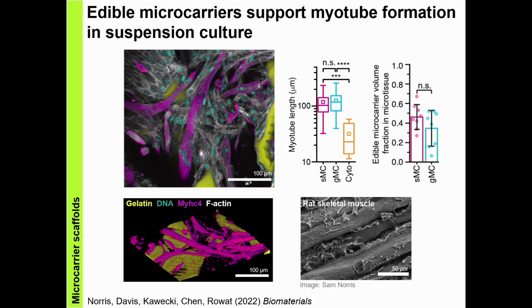So you can see that the myotubes notably are spanning hundreds of microns. In fact, they might be even longer, but the field of view limited us to this analysis of myotubes that are hundreds of microns. And we also assessed the volume of the microcarriers, which is between 30 to 40% or so, compared to the volume of the cells in these microtissues.